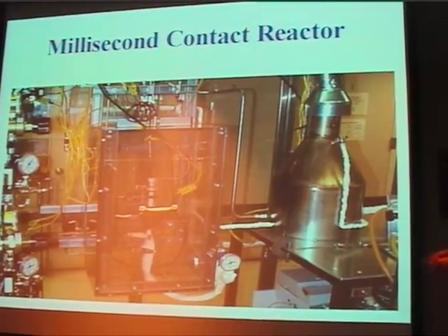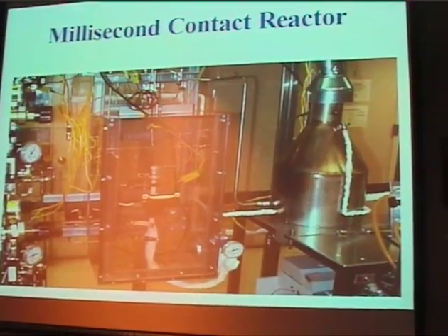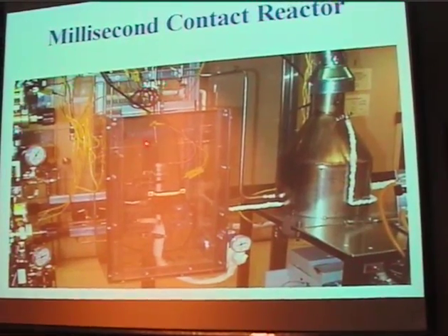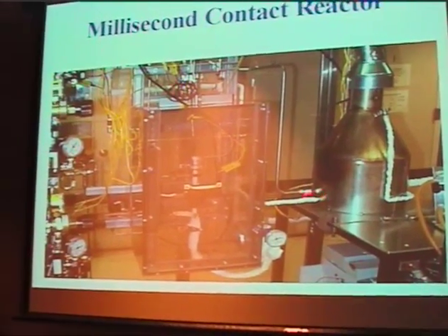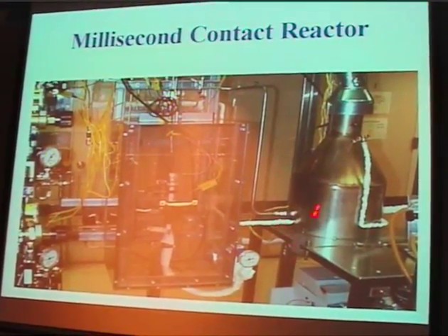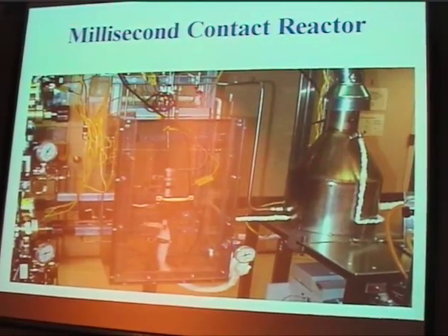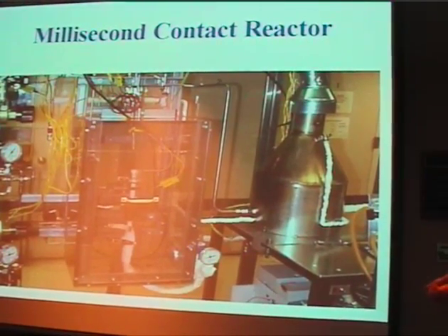So we designed and built a number of millisecond contact time reactors for our initial catalyst screening. Primarily on the left you have the gas manifold system. This goes over to the reactor itself. We had it in an explosion-proof encasing. The product goes over to an online GC, only a slipstream would be analyzed, and then we would flare the remainder of the gases. That was a requirement of the state of Delaware.